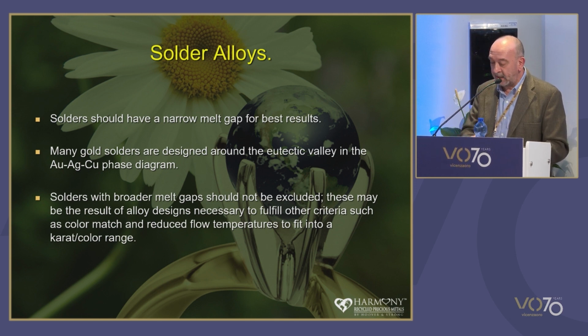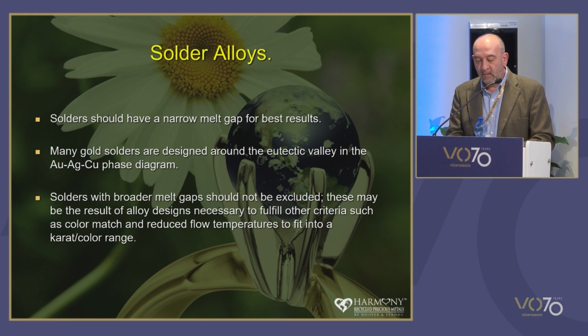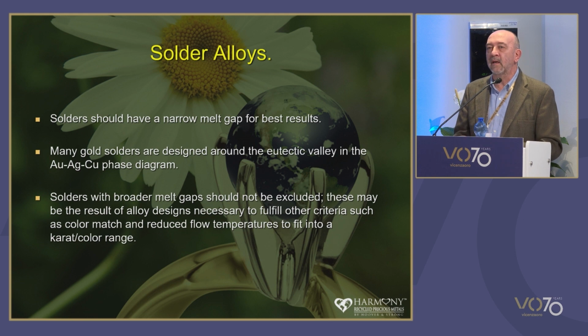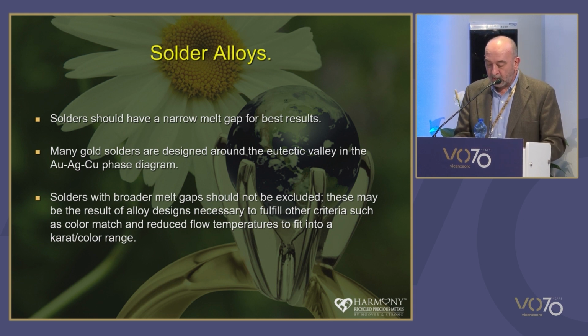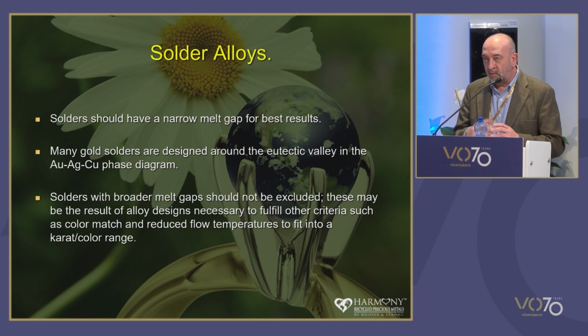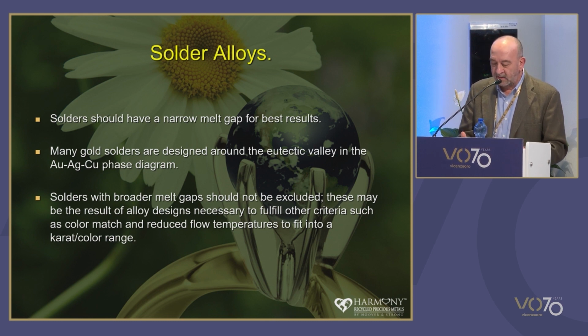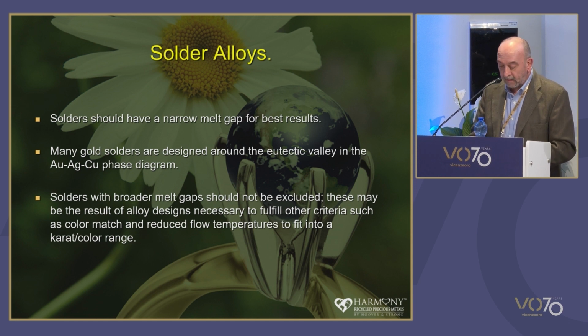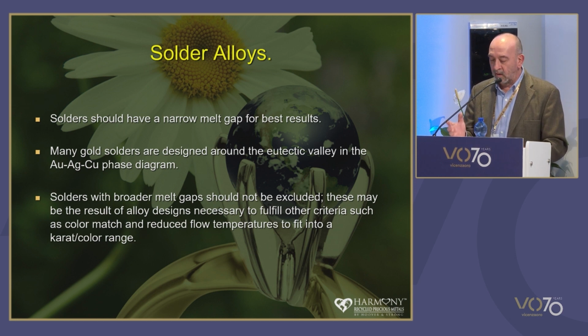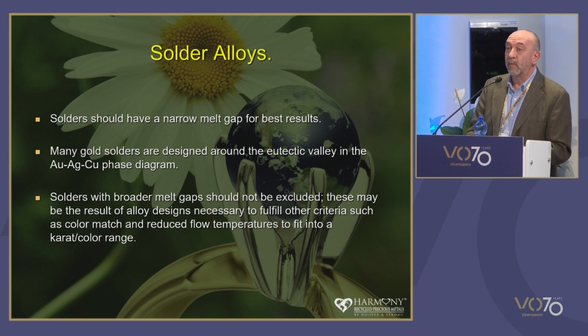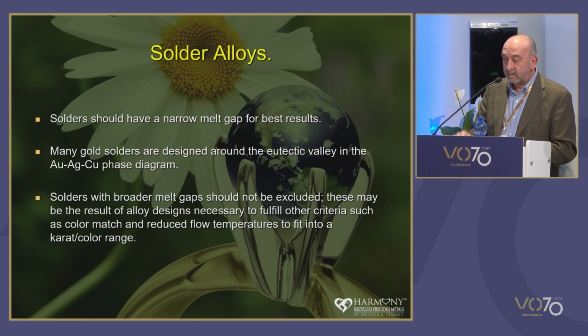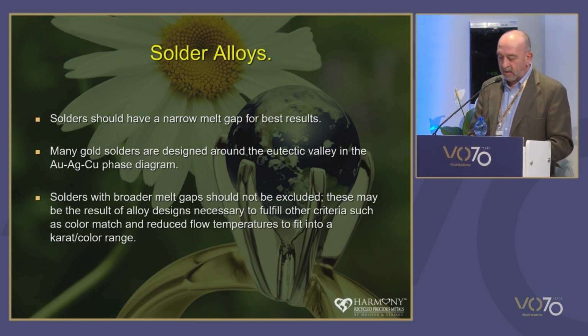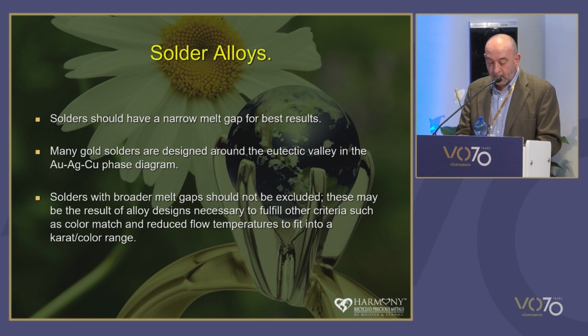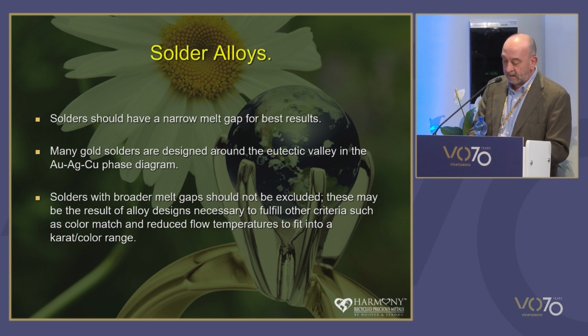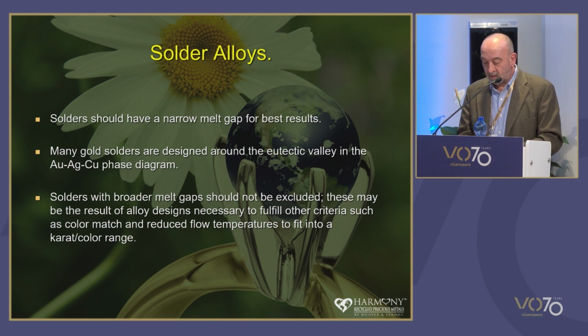As a general rule, easy and extra easy solders tend to be inferior to medium and hard solders as far as colour match goes, particularly when you're talking about yellow gold solders. The elemental additions you have to put in there to depress the melting point, such as zinc, indium, tin, gallium, and in the US, cadmium, are all commonly used. These tend to affect the colour, particularly when you're looking at yellow solders, and they bleach them. And it's well documented. I know in Europe you typically don't use cadmium solders, but they do in the US still. And cadmium does improve flow and improve wetting, but it's very toxic. So I'm not going to go into that, but I'm sure everybody understands the dangers of cadmium.